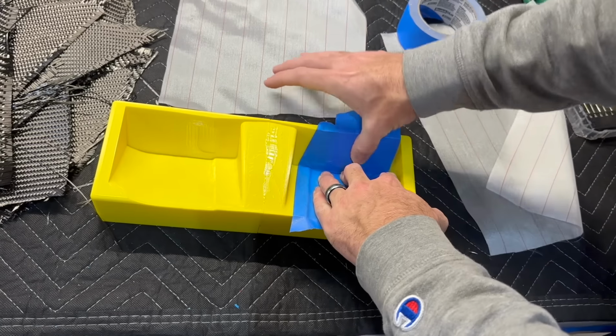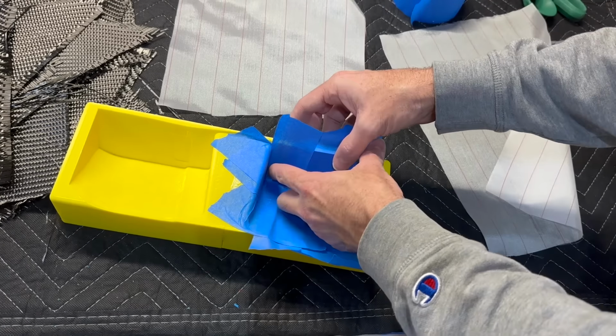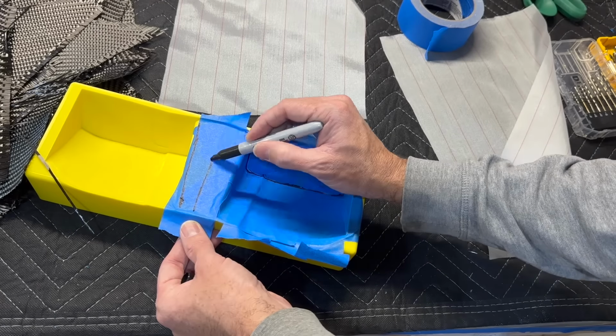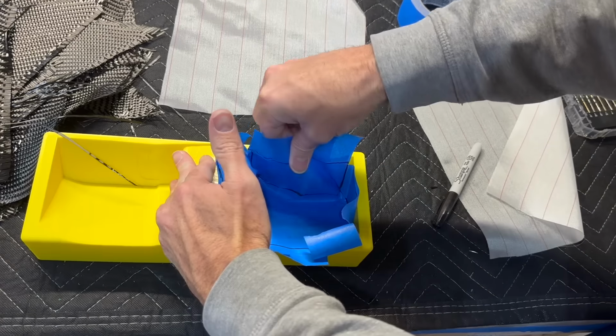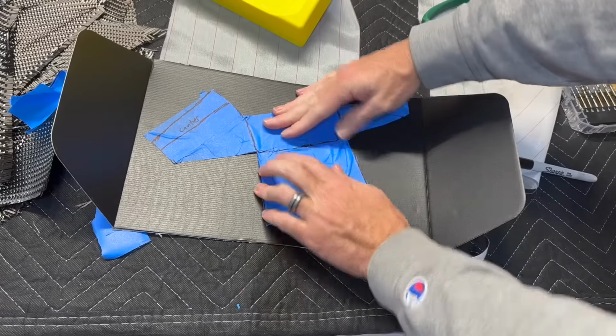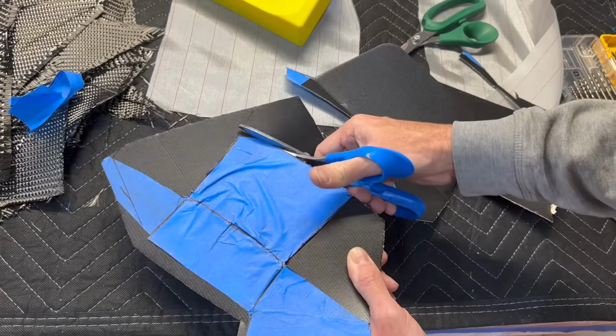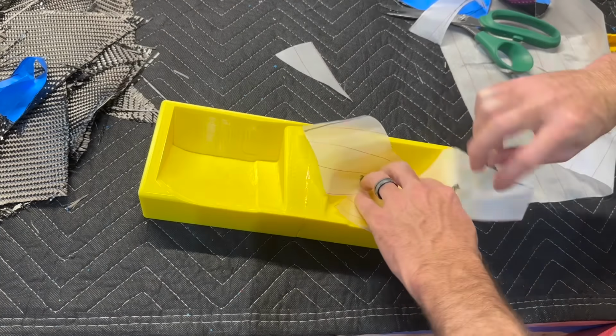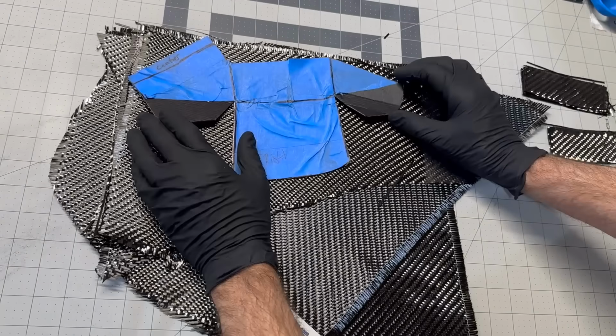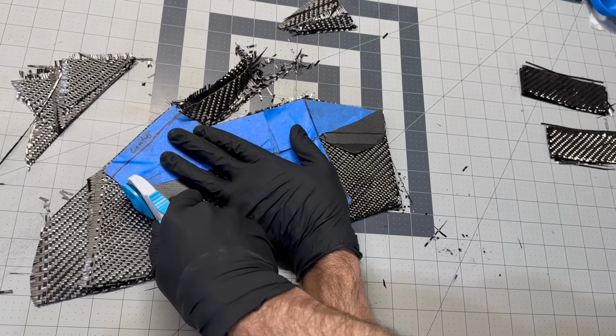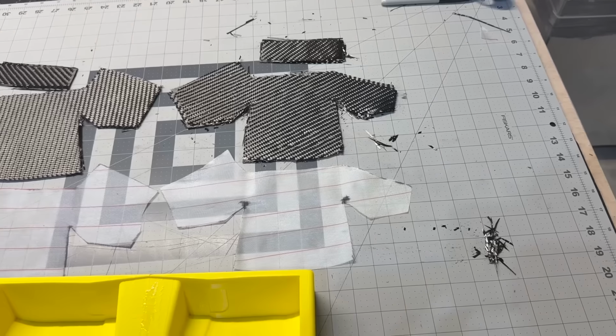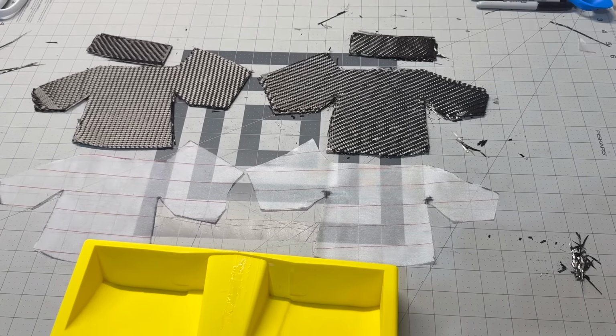to make this bracket. The first thing I'm going to do is lay down some blue painter's tape on the inside of this mold that I can then take out and make my template for both the peel ply and the carbon layers. With the template finished, it's pretty quick work to run around it with this roller knife and get the carbon cut out. The next thing on the agenda is to get the vacuum bag ready.